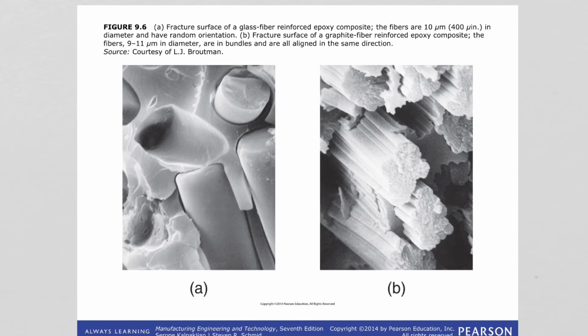In these microscopic images, we are seeing the fractured surface of glass fiber reinforced epoxy. So you guys are seeing, this is the matrix, and these are randomly oriented fibers within the structure. Of course, they didn't provide a scale here, but the figure description says the fibers are 10 micrometer in diameter and have a random orientation.